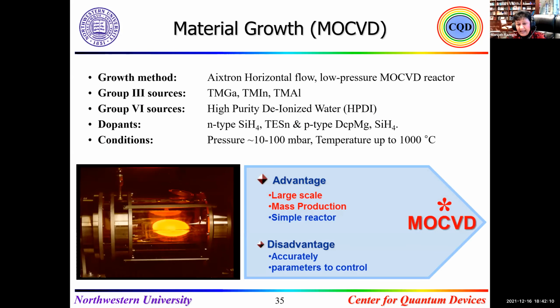When you do the growth, as you know, in any material the growth temperature has to be approximately two-thirds of the melting point of the material. There was nothing in the literature about the emissivity for gallium oxide.